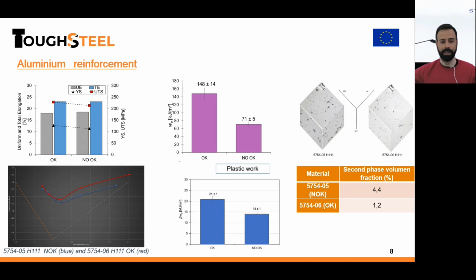The new material has a slightly higher FLD curve, but this cannot explain the different behavior during the forming of the component. So for this reason, we go deeper, analyzing the essential work of fracture of the two alloys, and here we really found the main difference between the two alloys, because the not okay, as you can see, has half of the essential work of fracture of the new chemical composition, as well as for the plastic work during the essential work of fracture test.